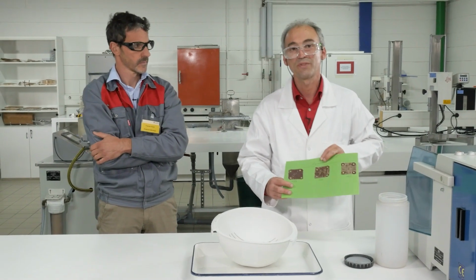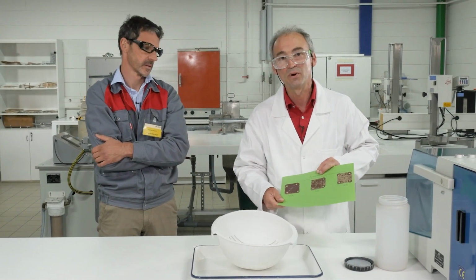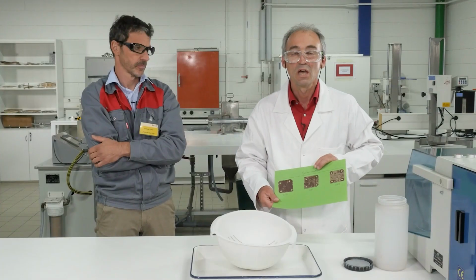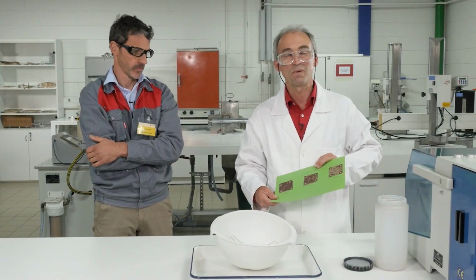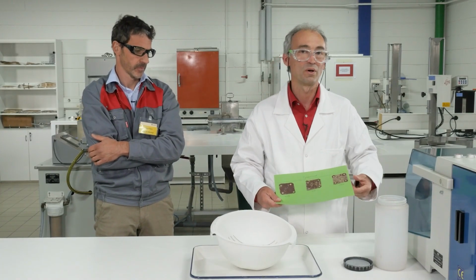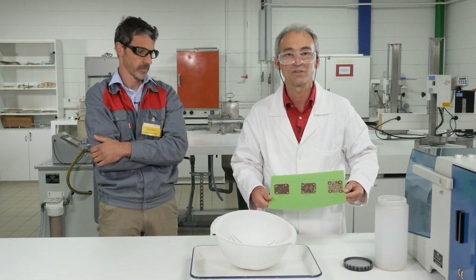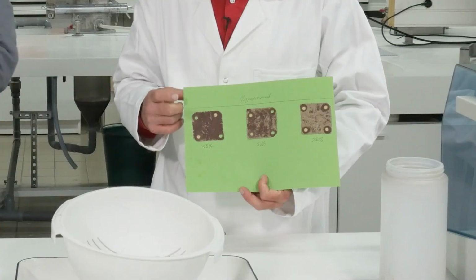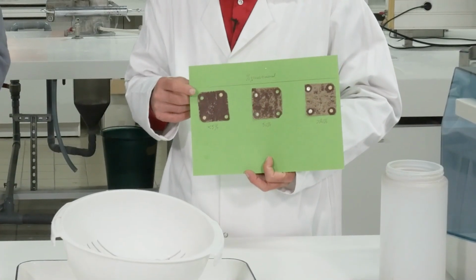So you have to know that for a given paper, we may get different results depending on the resin and depending also on the process, so that means the curing condition. But we have developed our paper with a more universal barrier, so that with most of the common phenolic and epoxy resin, we achieve a good performance. That means a very low level of removal.